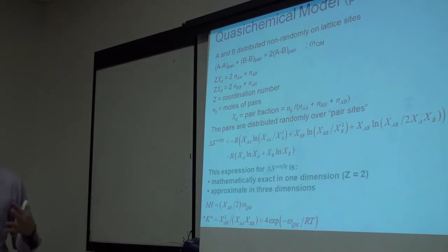But there's another thing: if omega is not 0 but small, then the model reduces to the regular solution model. Because as omega becomes small, the configurational entropy becomes very close to ideal.